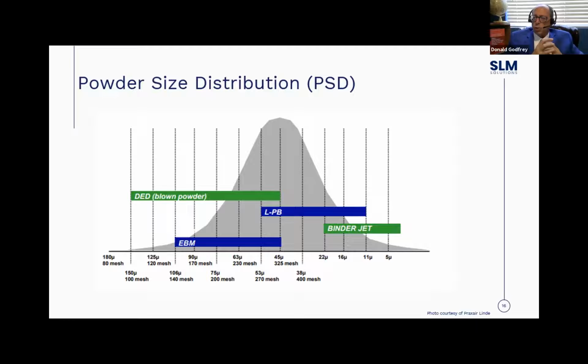And this powder is going to have a lot of different sizes to it. So if you're using electron beam, you're going to use powder in the size of, what is this, 100 micron size area. DED can use a lot of the larger size powder. The smaller powder in the 22 micron to the 5 micron is going to be used for binder jet. And then the laser powder is going to run in the 50 to the 11 micron area.